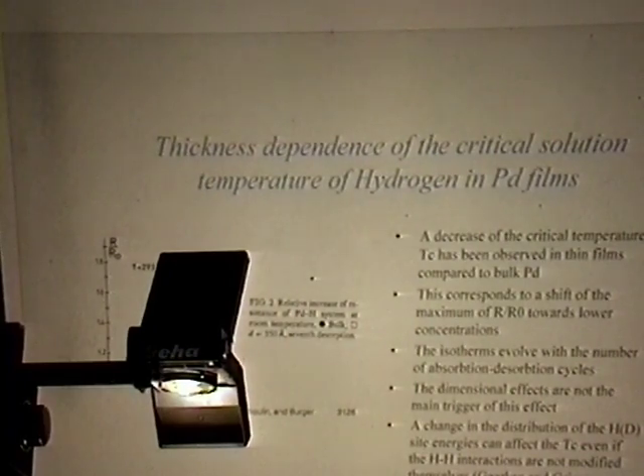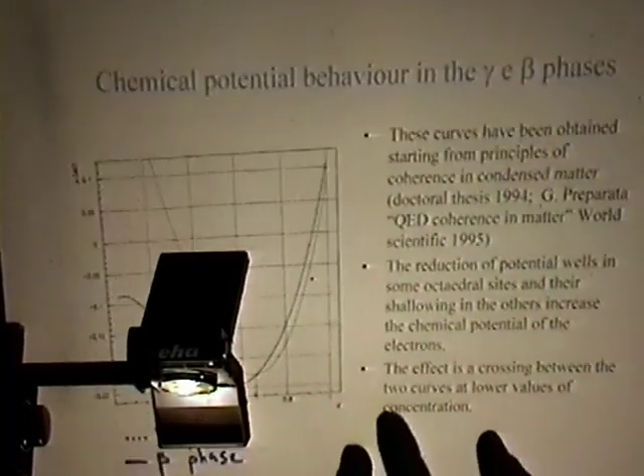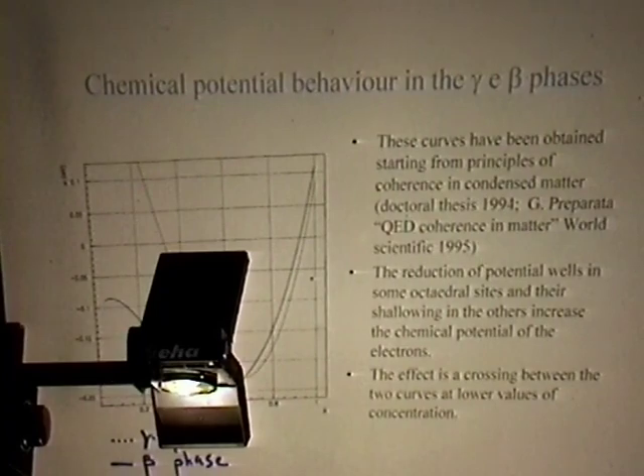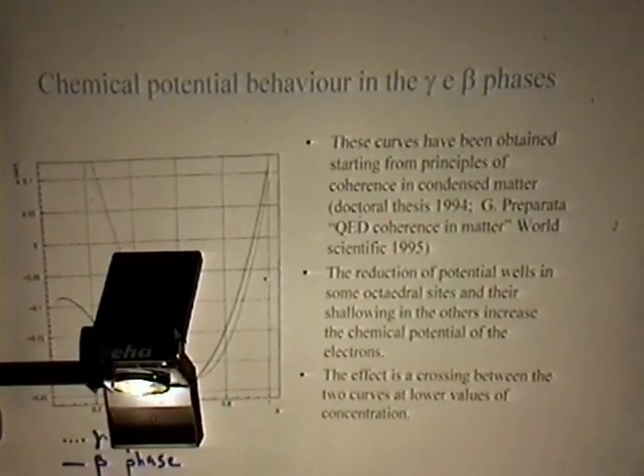Gleason proposed in 1983 an explanation based on the presence of defects and mechanical stress inside the sample. Probably there is a change in the distribution of the site energy inside the lattice due to dislocations and defects in the crystal. If there are many defects in the crystal because of the deposition procedure or metallurgical reasons, octahedral sites can be depressed in number. So there are fewer octahedral sites available for deuterons. This has an immediate effect on the chemical potential of the deuterons inside the metal.